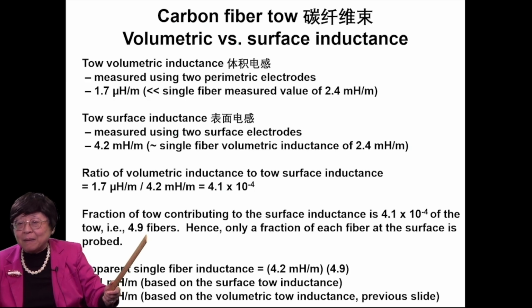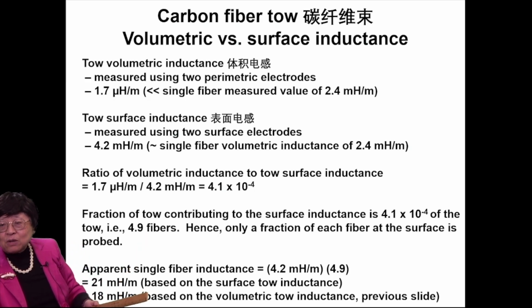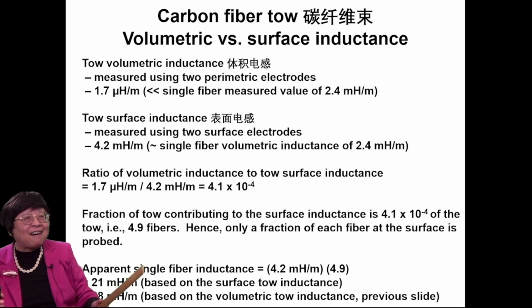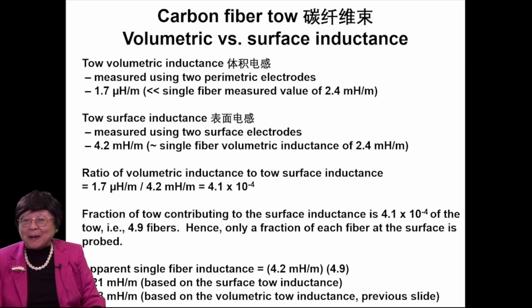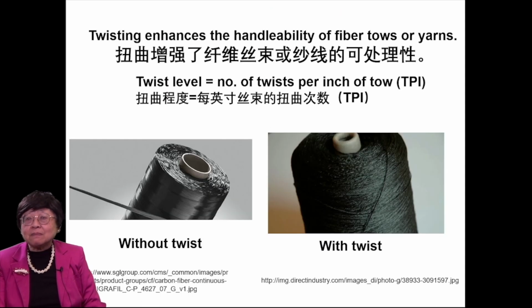Okay, and that equals 21 based on the surface tow inductance. But based on the volumetric tow inductance in the previous slide, it's 18. And so these are pretty close, 21 and 18. So things are consistent. Okay. The volumetric inductance and surface inductance results are consistent with one another. And the surface inductance is huge compared to the volumetric inductance.